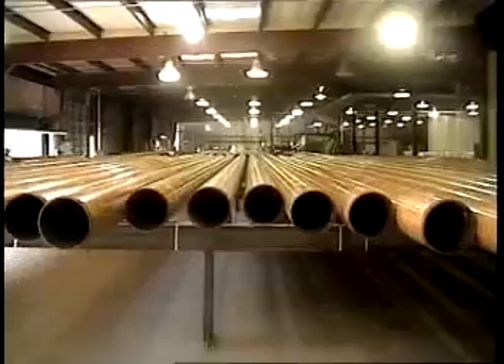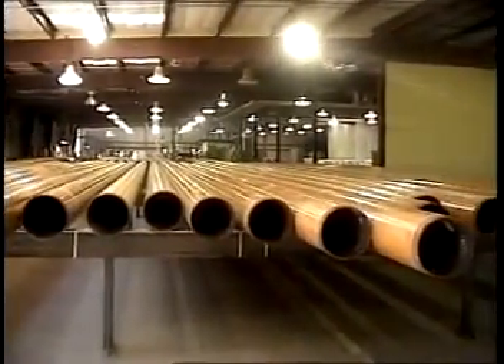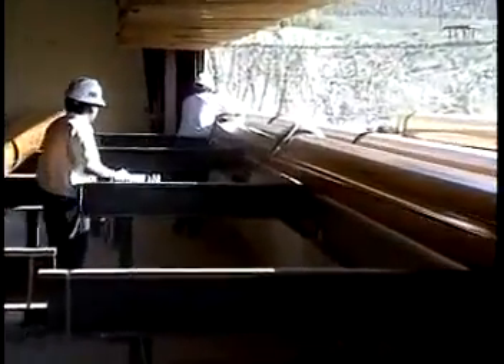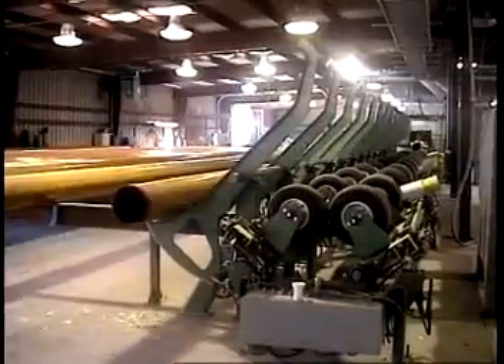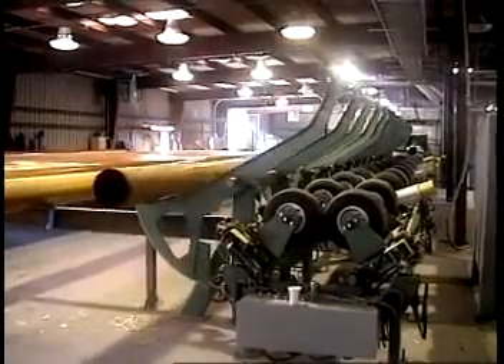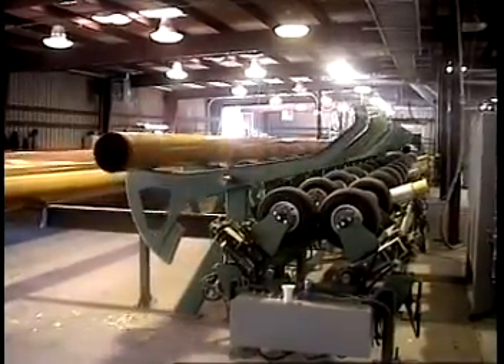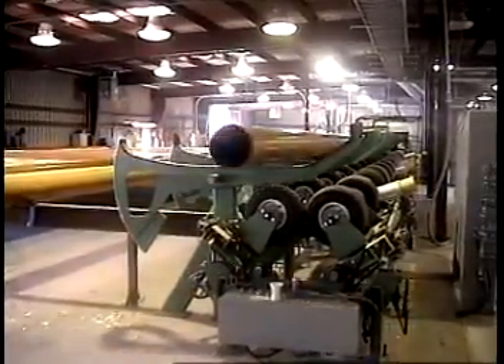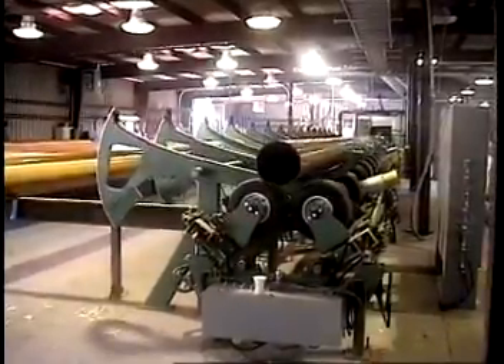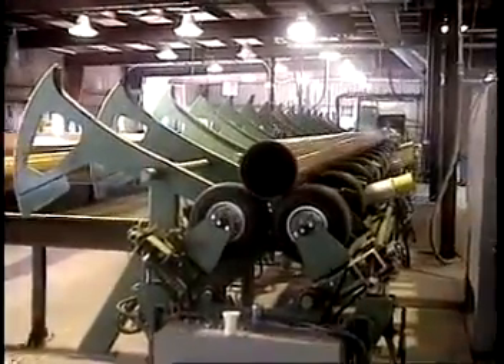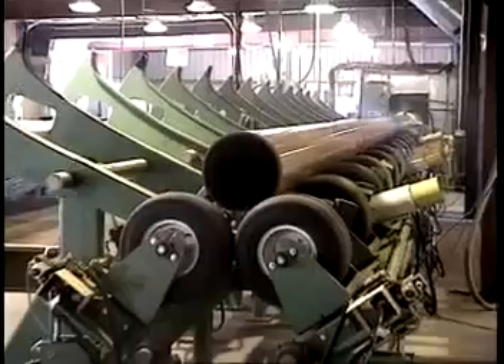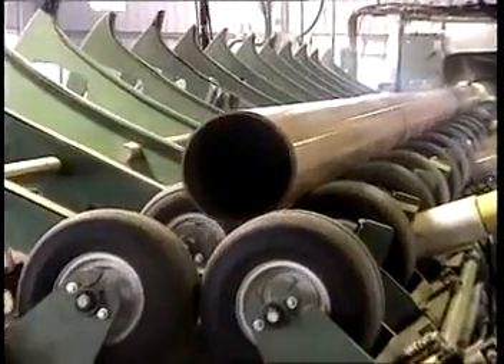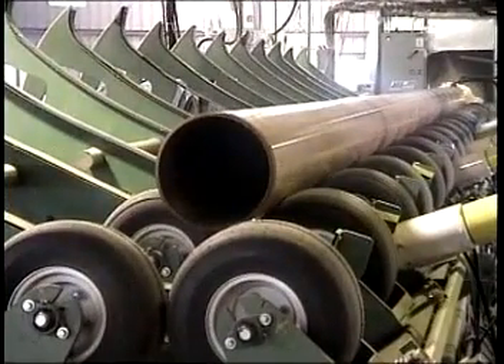Perma Pipe transported the coated piping from the laydown area to the insulating and jacketing building. The building was modified to allow the piping to be side-loaded through the wall onto the input racks. Once on the input racks, the piping was visually inspected and the coating was holiday tested at 2500 volts. Before insulating, any damage was repaired by abrading the FBE locally at the area and coating it with an epoxy patch kit. The piping was automatically loaded onto the electrically powered skewed feed conveyor.